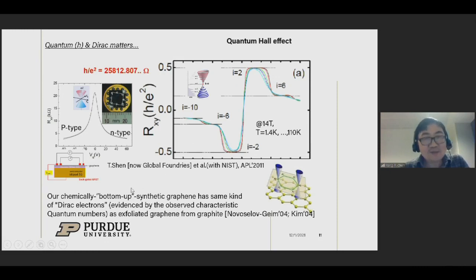quantum Hall effect. First of all, you can make a device simply by putting a few contacts. If you have a large film like this, you can transfer it onto a doped silicon substrate with some oxide dielectric layer, so you can apply a so-called backgate voltage, tune the carrier density, tune the Fermi level across the Dirac point from valence to conduction band. So that's all fine. And what's interesting is if you, for example, pass a current through two contacts, and measure the voltage of resistance across, the so-called Hall effect,